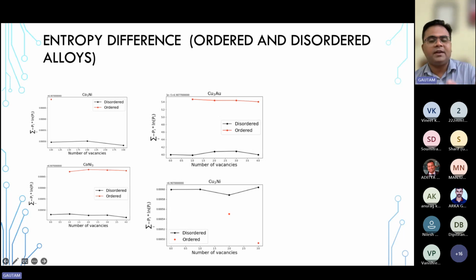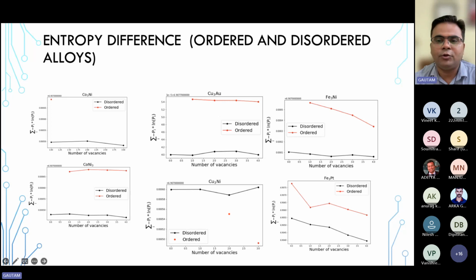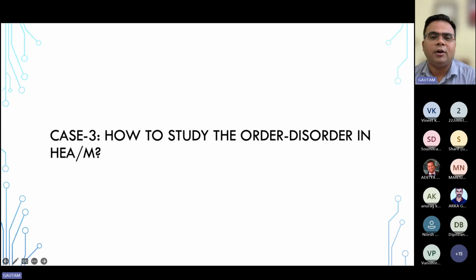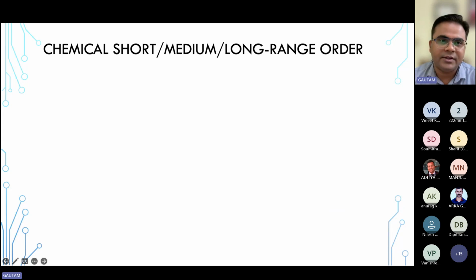So we are now talking about a range of different cases, and we are able to make predictions about the order-disorder just looking at the information entropy parameter. We took it to other cases also, and were able to make predictions at room temperature for iron 3 nickel and iron 3 platinum also. So for a range of cases we are able to make predictions about the order-disorder transition. This is for binary alloys. Can we do it for high entropy alloys or materials?